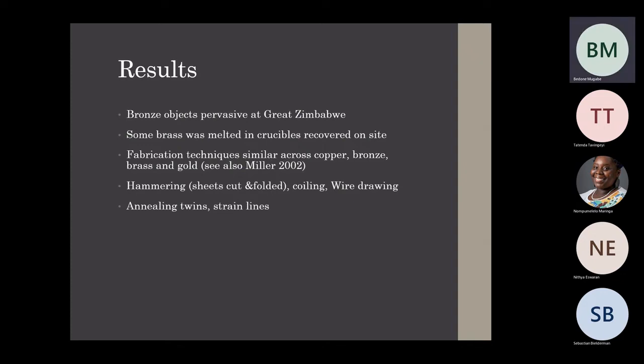So based on the analysis that we had, what we managed to denote is that of the 26 samples, bronze objects were very pervasive. Out of the 26, 21 samples were mainly low tin bronzes, right? So this actually adds to the data that we have from Miller 2002, Bandama et al. 2013, that shows that the ancient people that lived at Great Zimbabwe were able to manufacture bronze and brass, they were able to mix copper and tin to formulate bronze, copper and zinc to formulate brass.